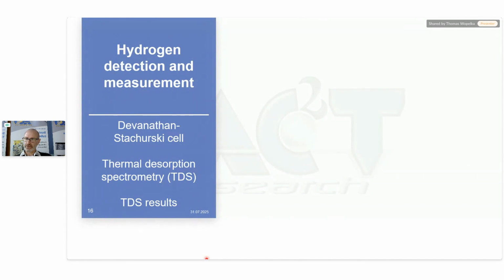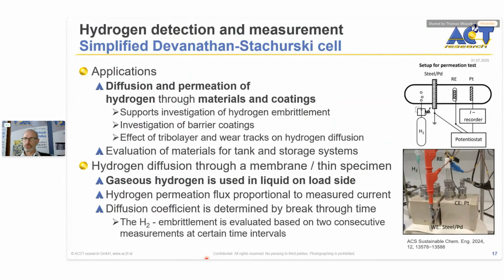Further equipment we got recently is the Devanathan-Stachurski cell and the thermal desorption spectrometry. Just a short overview about this simplified version of the Devanathan-Stachurski cell, which is used for determining the diffusion and permeation of hydrogen through materials and coatings. Thereby, it supports the investigation of hydrogen embrittlement, the investigation of barrier coatings to prevent hydrogen diffusion, and maybe you can also measure the effect of a wear track on the hydrogen diffusion of a specific sample.